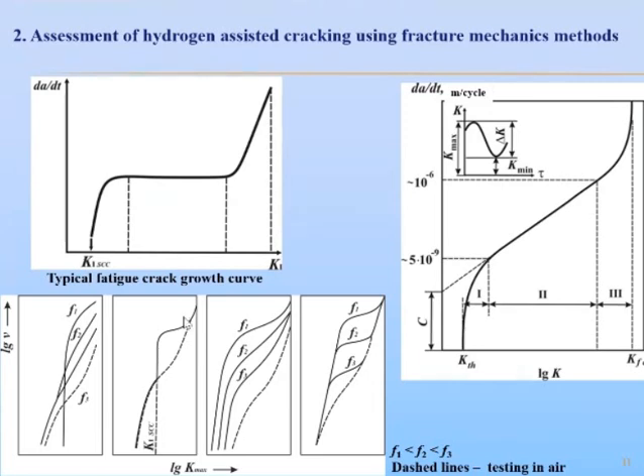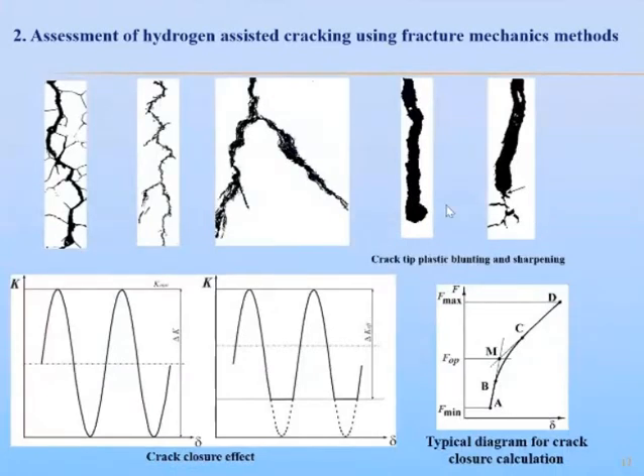Stress corrosion fatigue, and different frequency causes different plateau curves. Corrosion and hydrogenating environments can change the mechanical situation, which usually is not detected by the nominal stress intensity factor, a value calculated on the basis of specimen geometry, a scheme, level of loading and crack length. In this case, possible crack branching, micro, macro, intergranular, etc., and blunting are not taken into account.